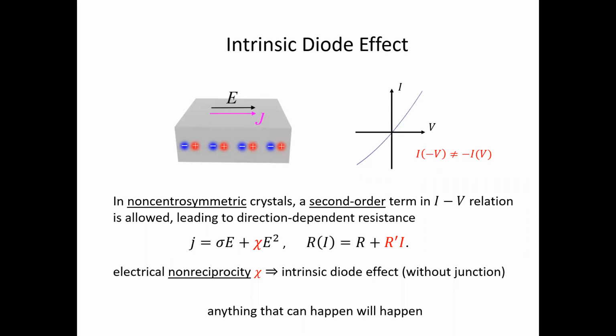If you look at the IV characteristic, in addition to the linear term, that's the simple Ohm's law, there could be a second order quadratic correction. If this is present, it means the resistance will be different when you apply voltage in opposite directions. So there's a direction dependent resistance. This kind of behavior without any physical junction is sometimes referred to as electrical non-reciprocity. If it's present, it will lead to a diode effect: the resistance depends on the direction of the voltage, yet without invoking any junction.